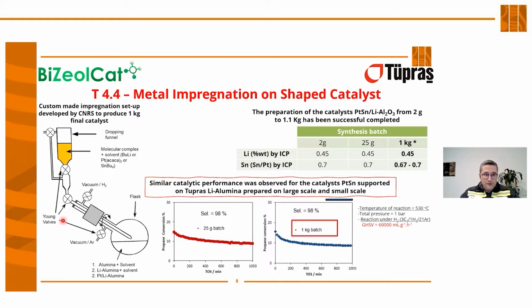On the left side, this was developed by our partner CNRS in order to produce 1 kilogram of final catalyst for the impregnation of platinum tin. The preparation of the catalyst, platinum tin on lithium doped gamma alumina, scaling from 2 grams to 1.1 kilogram has been successfully completed.